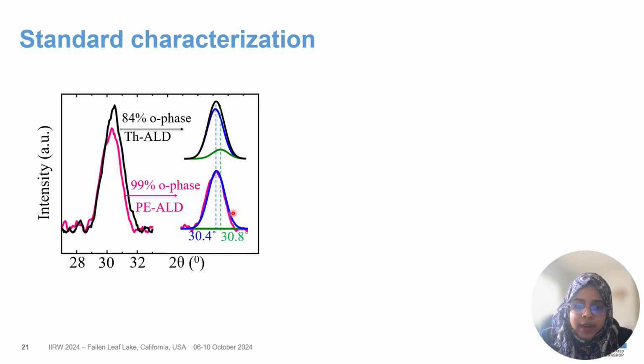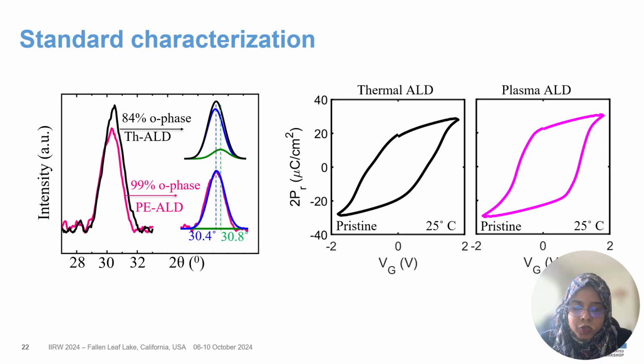Next, we have done the standard characterization of our HZO film for both the thermal ALD and plasma ALD devices. What we are seeing is that plasma ALD has a higher orthorhombic phase compared to the thermal ALD process. And this is also recorded in the electrical measurements. These are the PV loops coming from the thermal ALD and plasma ALD devices, measured in the pristine state at 25 degrees Celsius, and we are seeing the same trend, that the polarization of the plasma ALD device is better compared to the thermal ALD device.